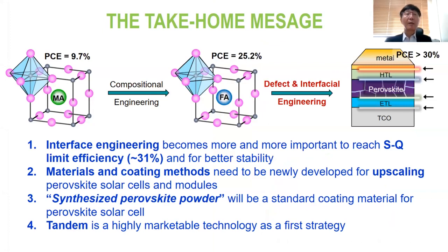Now let's wrap up my talk. In 2012 we started with 9.7% efficiency on the solid-state perovskite solar cell, and during the past 10 years, people have devoted a lot to increasing the efficiency by compositional engineering, and eventually a PCE of about 25.2% was recently achieved. And to go up further, to 30%, reaching the Shockley-Queisser limit, then the interfacial